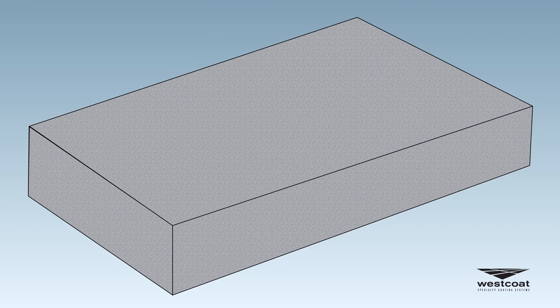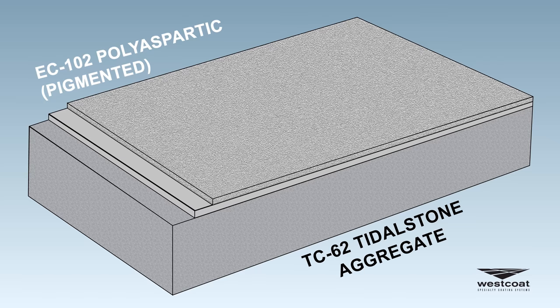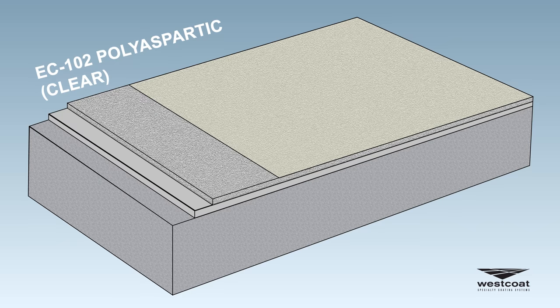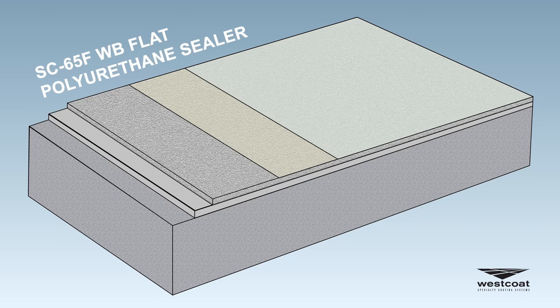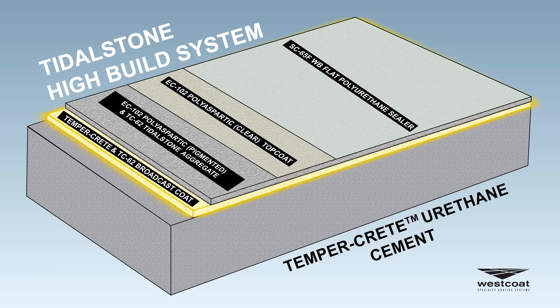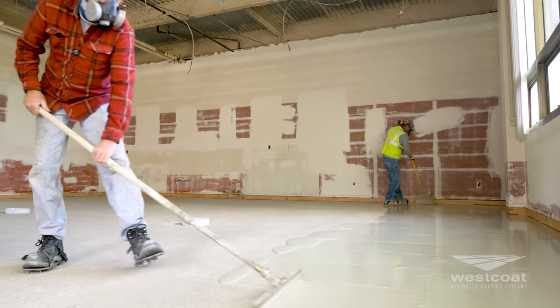The Tidal Stone flooring system is available in a thin film or high build offering. The thin film system includes EC12 epoxy primer, EC102 polyaspartic with TC62 Tidal Stone Aggregate Blend broadcast, sealed with EC102 polyaspartic and SC65F water-based flat polyurethane sealer. The high build system features the same overall assembly but incorporates Temper-Crete urethane cement technology in place of the EC12 layer for enhanced bond strength, increased moisture tolerance, and produces a high build self-leveling flooring option with extended service life and warranty.